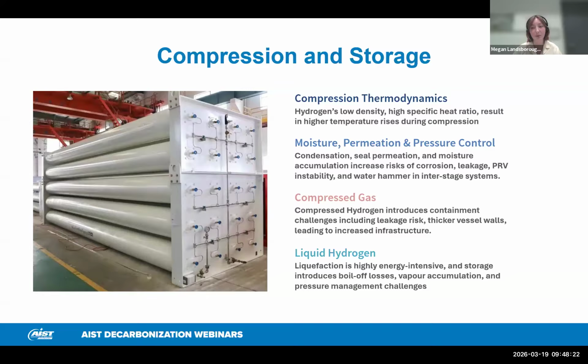Now moving on to liquid hydrogen. As Ian had mentioned, gaseous hydrogen can be liquefied by cooling it to below -423 degrees Fahrenheit. It takes a lot of energy to liquefy hydrogen, and using today's technology, this actually consumes more than 30% of the energy content from the hydrogen, and therefore it is extremely energy intensive.